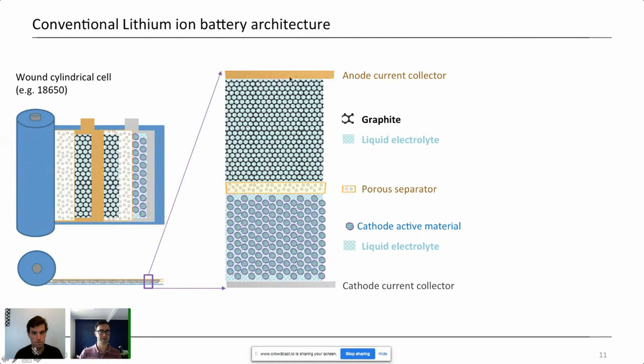So starting from the top here, this sort of copper-colored material is just a copper foil. That's a current collector that delivers the electrons to the battery. The next layer here is a layer that includes graphite. The graphite is the host for lithium when the battery is in the charged state. So lithium sits up here in this second layer at the top when the battery is charged. Graphite is just the host for lithium. So lithium sits in between planes of graphite atoms. Also, between the graphite particles, there's a liquid electrolyte that's responsible for doing the ion conduction of lithium between